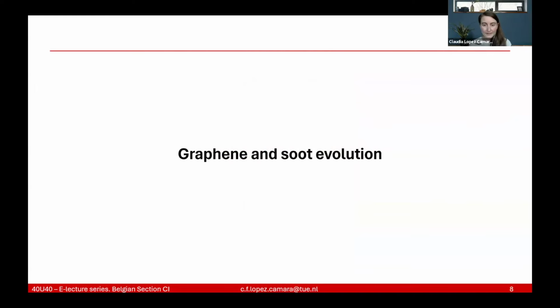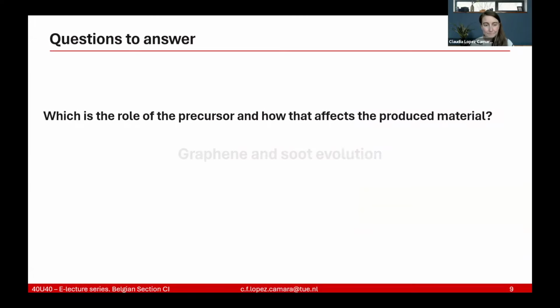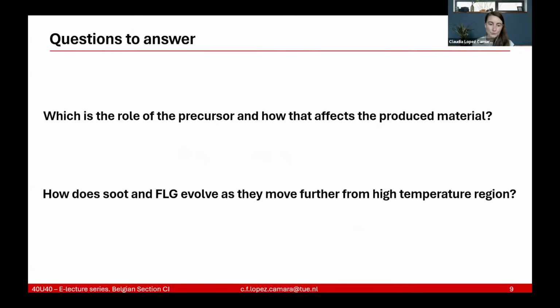So look, after this overlook of all the techniques, we will look into the graphene and soot evolution. And you might think, why do we want to look into that, because graphene and soot are very well known. However, when we use gas phase synthesis to create them, we did not yet know the role of the precursor and how that affects the produced material. We also had another question that we wanted to answer: how do soot and few layer graphene evolve as they move further from the high temperature region? So we wanted to know, first of all, what the precursor will create, and second, once the material is created, how does it look until the time that we can actually collect it in the filter?